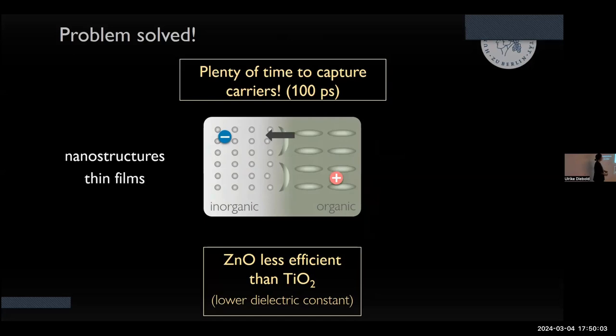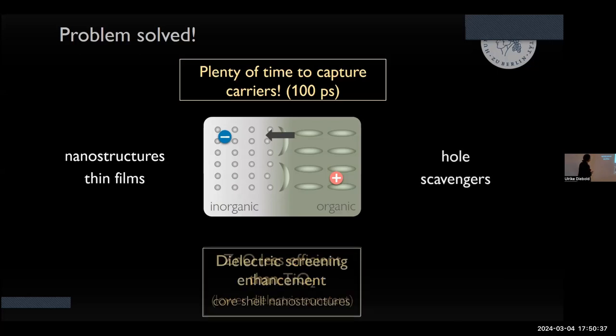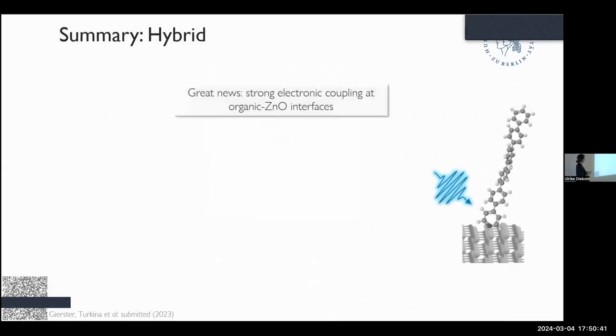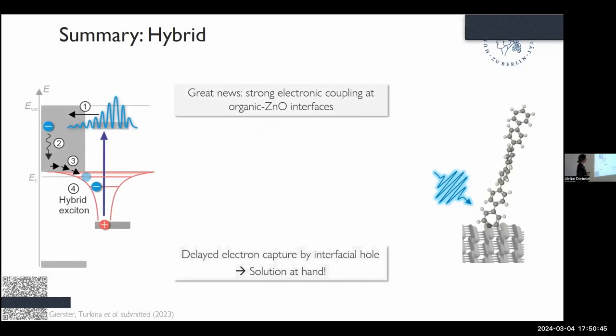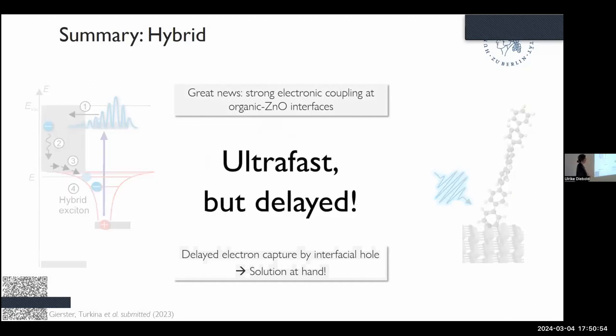So if we can enhance this time or capture either the electrons away from the zinc oxide or the holes in the organic before the electron moves towards the surface, then we can charge separate. So I think it's possible to use zinc oxide in light harvesting systems if you understand that you have to do something about the screening and that you have to take out the electrons or holes quickly enough. So there is charge separation. And I would like to summarize it with great news, strong electronic coupling at organic zinc oxide interfaces, and we might have a solution to make zinc oxide feasible. So we have ultrafast electron transfer and hybrid exciton formation, but it's delayed by 100 picoseconds.